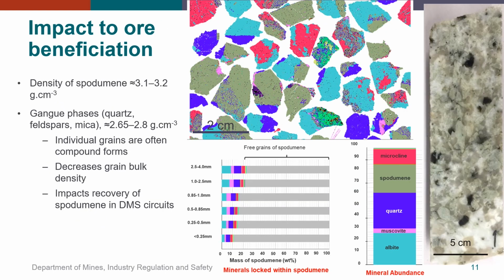After crushing the ore, one of the main separation techniques to remove gangue phases such as quartz, feldspar, and mica from spodumene exploits the difference in the physical properties of these minerals, namely the difference in their density. Spodumene has a density of about 3.1 to 3.2 grams per cubic centimeter, whereas the main gangue phases have a lower density in the range of about 2.6 to 2.8.